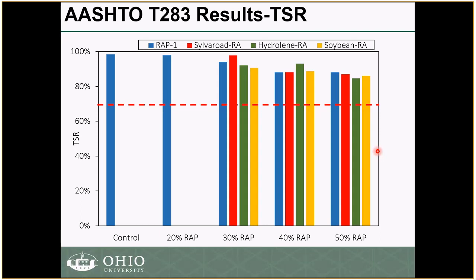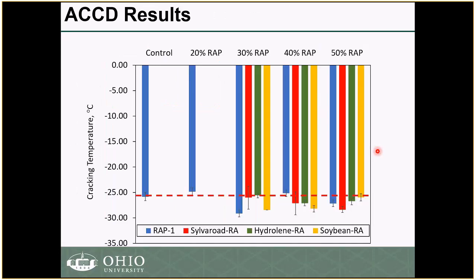In terms of the durability or moisture damage resistance, as measured by the TSR, the tensile strength ratio, typically it's required to be between 70 and 80 depending on what type of mix, and as you can see, it met both the 70 and 80, all of those were above 80%. In general, using RAP will not result in any moisture damage if your mixture is well designed, meaning that you have designed it so that you have a good amount of asphalt binder, and this is what you see. So again, the TSR for all mixtures was beyond the 80, and it met the criteria.